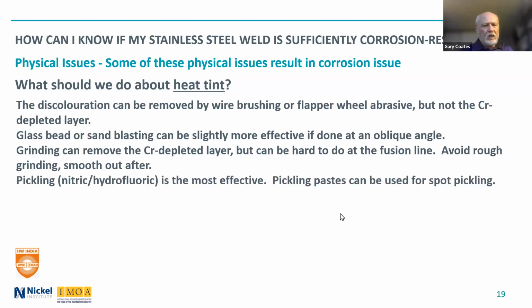And again, the nitric hydrofluoric acid mixtures are the most effective. And the pickling pastes are used for spot pickling. So if you just have a small amount of weld to do, you can just put on the pickling paste. You can also put it on the iron contamination areas too as pickling paste, and it works well.